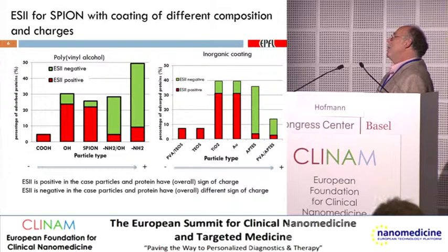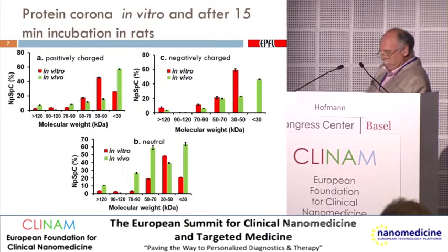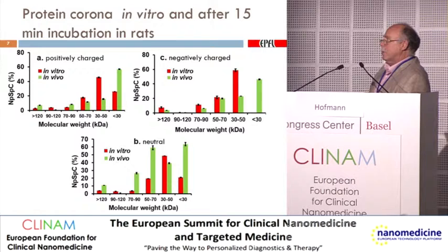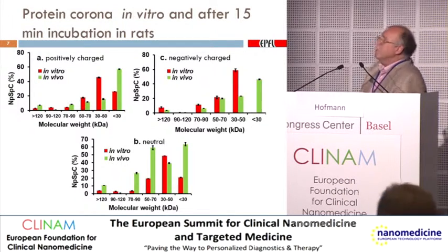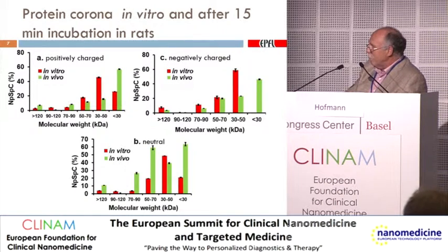And if you now think you know more or less what happens in the system, if you do the following experiment: we have the in vitro, shown before, with the same serum, rat serum for example, and then you put the same particles, with the same charge, into rats by intravenous injection, and after 15 minutes you take the particles back out of the bloodstream, and you look at the proteins which are on the surface. We see different proteins, the same particles, the same blood or serum, both rats.